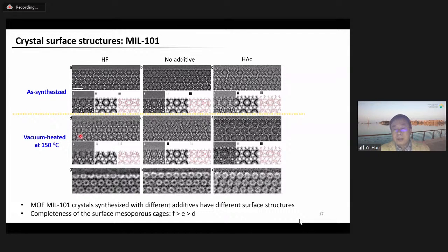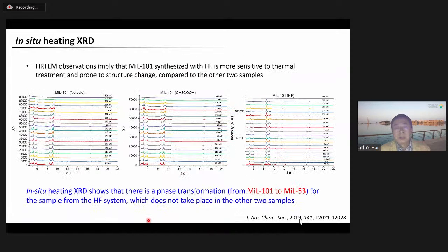And another interesting finding is that during the vacuum drying process, only the sample synthesized with HF has its crystal surface changed from closed to open. Well, the other two samples retain their original surface structure. So this observation suggests that the sample synthesized with HF has some different property from the other two samples, and it should have lower thermal stability, because this surface structure change is driven by drying at 150 degrees.